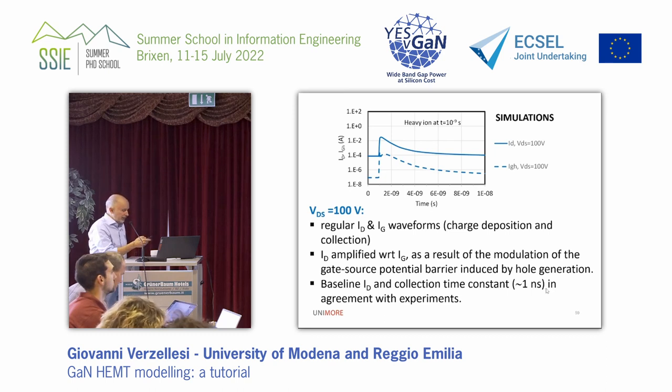These are simulations at 100 volt, okay? And what we obtain in our simulation is quite regular ID and IG waveforms related to charge deposition and collection. Okay. This is the time of ion arrival. You have a peak in both drain current and gate current. And basically, electron-hole pairs are generated.